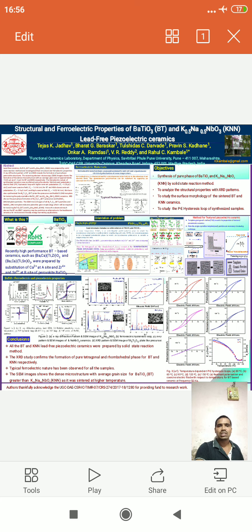after 120 degrees Celsius, the tetragonal phase of BaTiO3 becomes a cubic phase. So after that it does not show ferroelectric behavior. There is a linear behavior of polarization versus electric field at 125 degrees Celsius. We can easily see that. After 120 degrees Celsius, the BaTiO3 unit cell converts into a cubic unit cell. There is also a Pr versus temperature plot, so remnant polarization also decreases when we increase the temperature.